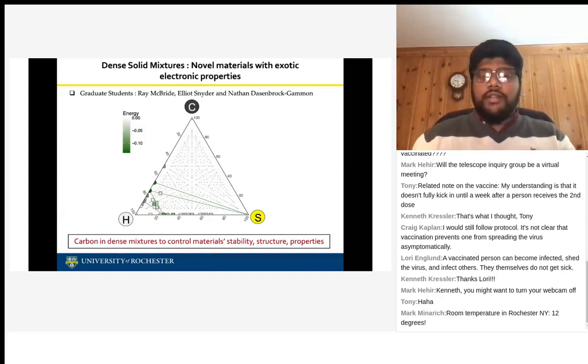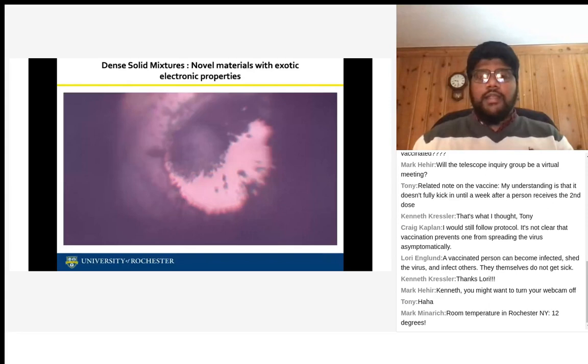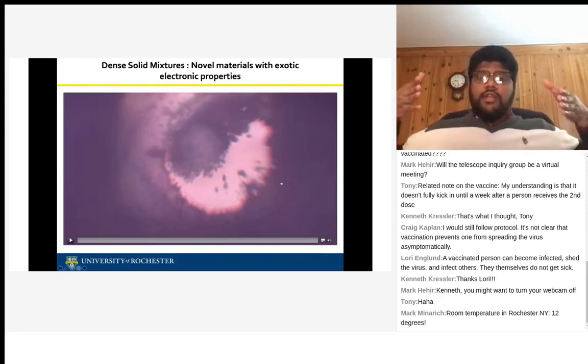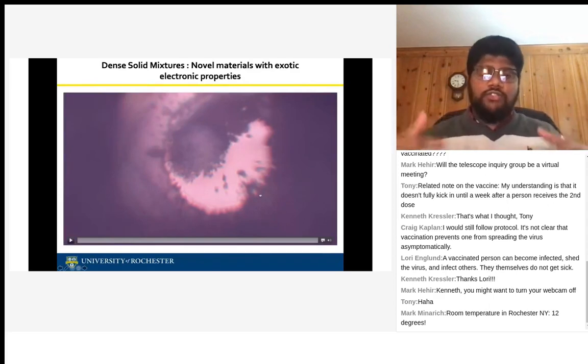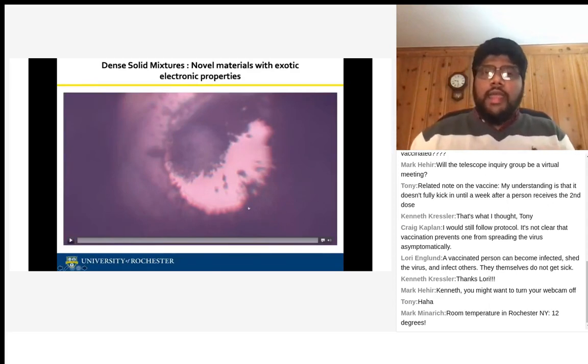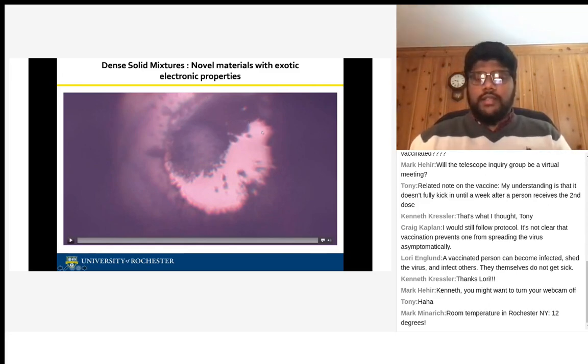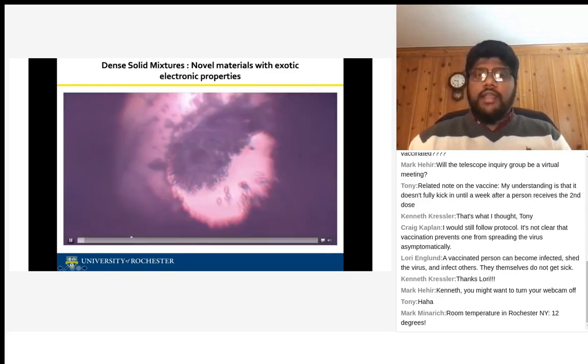So I'm going to show you the new material, the magic material that we made in our lab. What you're seeing in this image is the image through the diamond anvil itself, because it's transparent. And this is the carbon and sulfur mixture, this dark area. This light, transparent area is pure hydrogen. So what we use is a photochemical technique. I'm shining my 532 green laser right here into your setup, which is your sample.